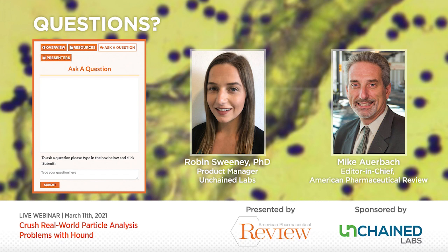Yes, you can. If you're going to do this, we would recommend that you use Raman first and then do LIBS. And that's because LIBS does ablate a small amount of the particle, so you don't want to do that until after you've collected your Raman.